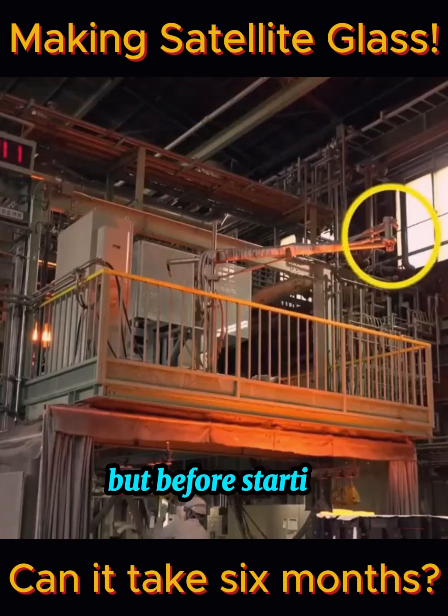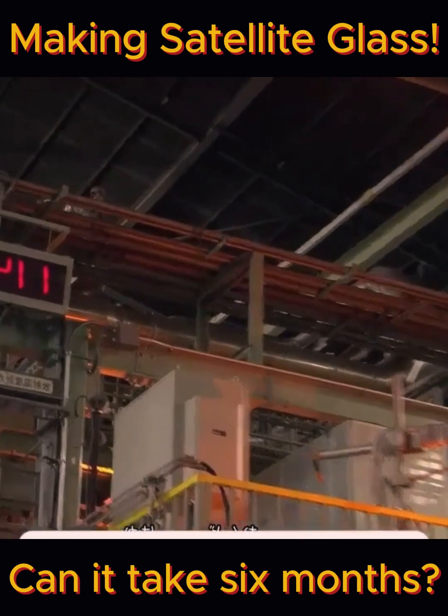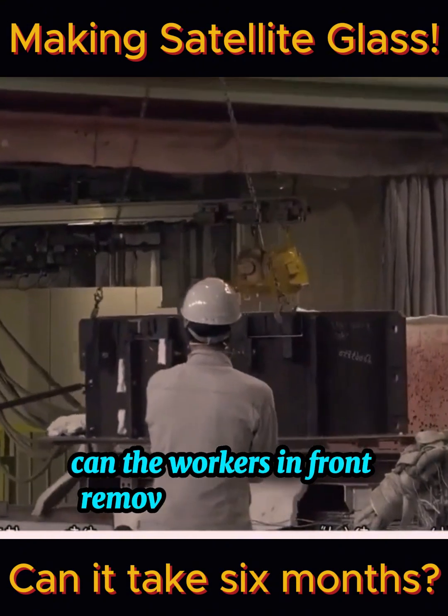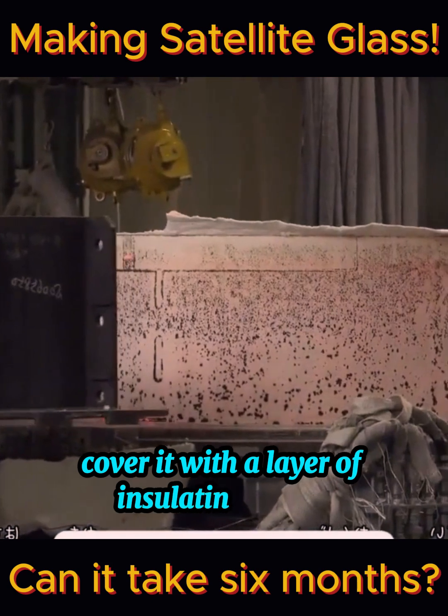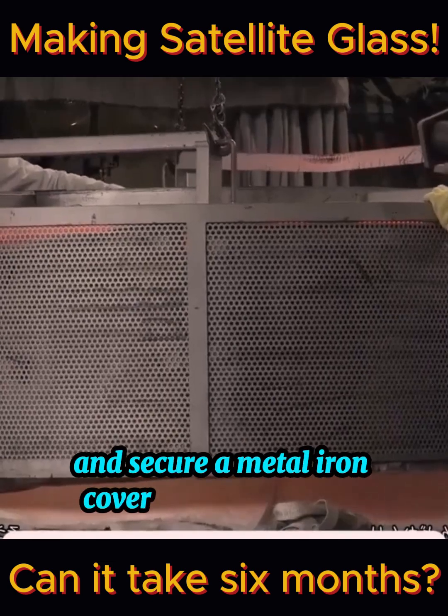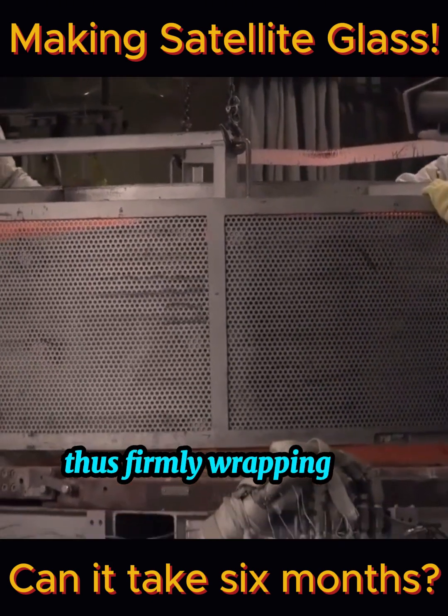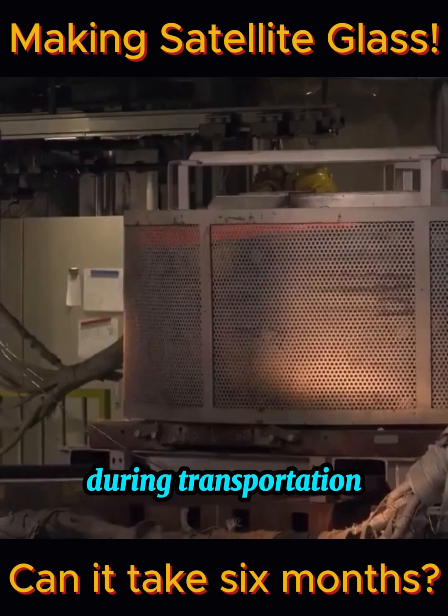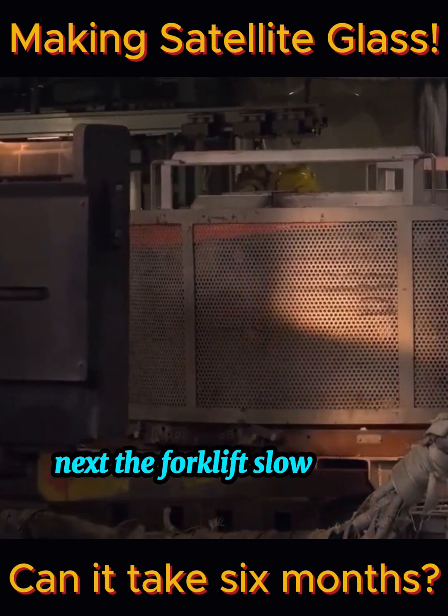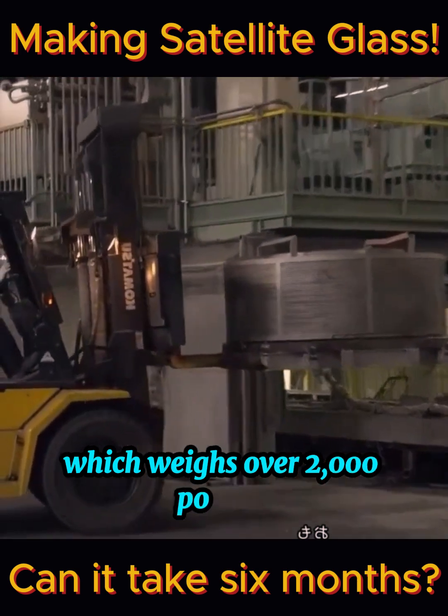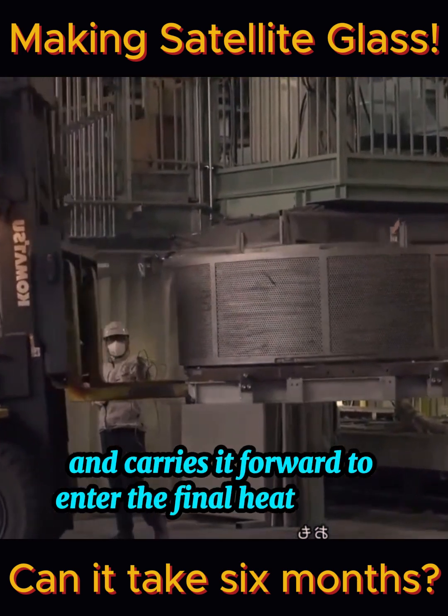But before starting, a thermometer must be used to measure it. Only when the temperature reaches the required specification can the workers in front remove the outer mold, cover it with a layer of insulating cotton, and secure a metal iron cover around the glass, thus firmly wrapping the glass to prevent bumps during transportation. Next, the forklift slowly lifts the glass, which weighs over 2,000 pounds, and carries it forward to enter the final heating step.